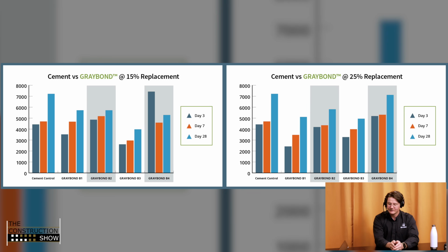So in B2, we used a calcium hydroxide blend with a little bit higher pozzolan and a little bit less of the calcium hydroxide. And in blend B4, we used a quicklime calcium oxide blend that was a little bit higher in overall calcium oxide and a little bit less in pozzolan. But our lab research actually showed that higher calcium oxide blend to be the better performer, but it would be a little bit more exothermic, and there were maybe some more challenges down the line having more of that calcium oxide in that mix.